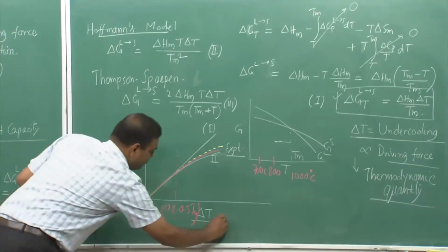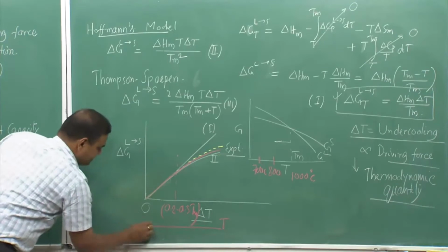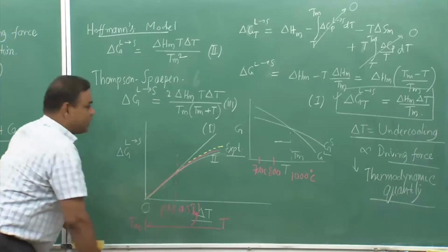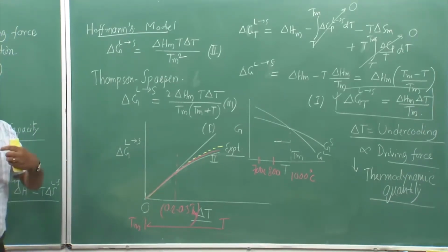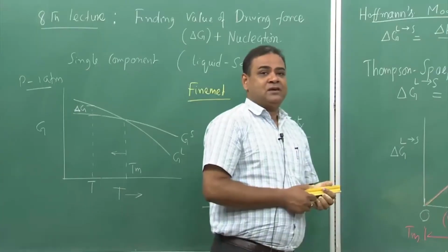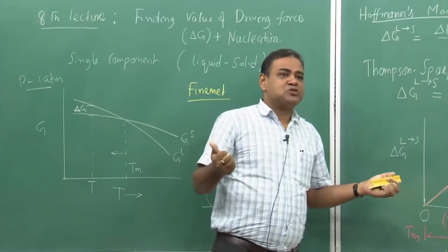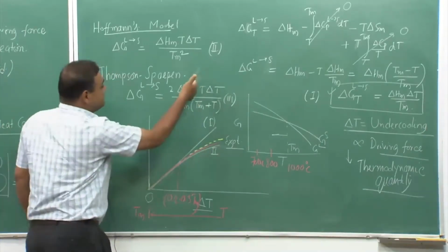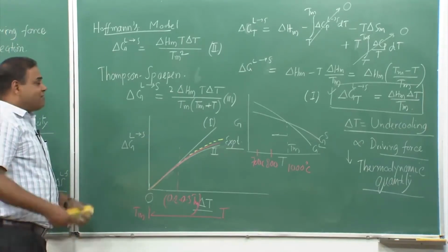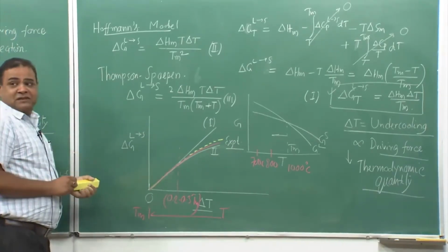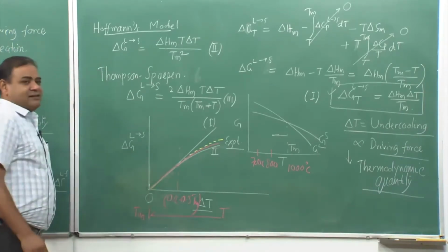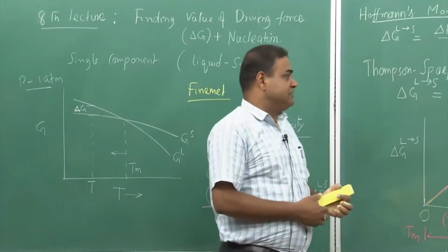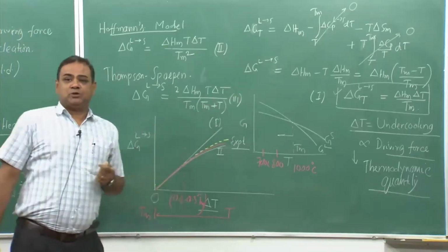So, if I try to plot in terms of temperature, then this particular temperature which is 0 is Tm. So, within this range, 200 to 300 degrees Celsius below Tm, we have most of the reactions over. Okay. So, that means we do not need such complicated expressions. We are okay with a simplified expression, since within the temperature range I would be concentrating on, it would not make any difference even if we use a very simplistic approach.